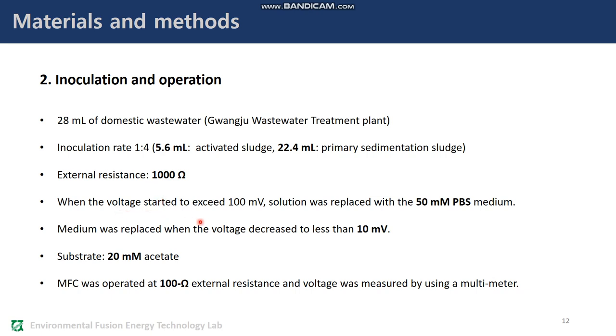When the voltage started to exceed 100 mV, the internal solution was replaced with the 50 mmol PBS medium. Medium was replaced when the voltage decreased to less than 10 mV. And then, 20 millimole acetate was added as a substrate. MFC was operated at 100 ohms external resistance, and voltage was measured by using a multimeter.